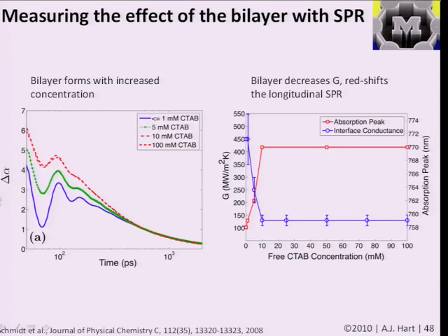And just really quickly, we can see this behavior as we start to increase the concentration of this surfactant molecule in solution. So we go from having no particles in solution, and you get this one kind of curve, so there's excitement and decay. And then as you start to increase the concentration of surfactant, the shape changes, and then above a certain concentration, in this case 100 millimolars, it stops changing again. So that indicates that you've kind of been assembling this bilayer, and then once you get this critical concentration, it's stable and it's not going to do anything else.